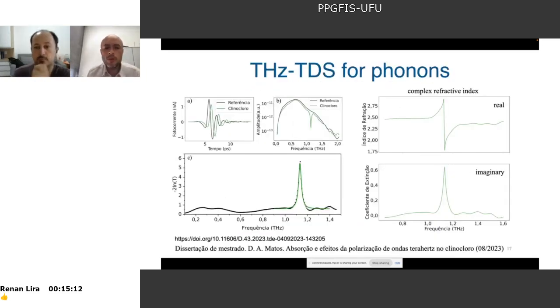Okay, so I want to show you here some example, maybe if you never used terahertz time domain spectroscopy, an example for phonons. How do you see phonons in this kind of experiment? Here I'm using some figures from a master's thesis from my student that you can find in this link. So first you need to measure the reference, right? The reference here is this black line. The reference means if you have a sample, for example, with a substrate, you measure only the substrate. If the sample doesn't have a substrate, then you need to transmit the light only through the air.